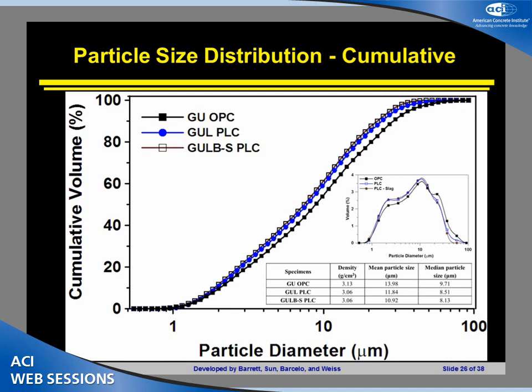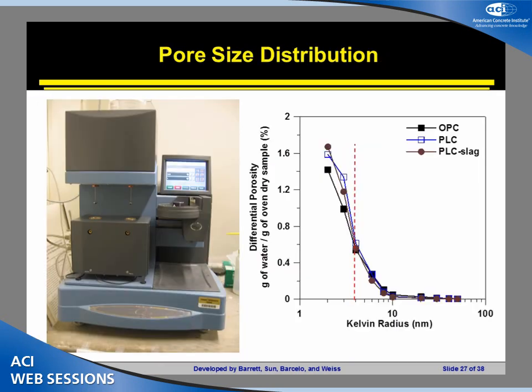Here you can see that there's a slight shift to the left, but we don't see that sort of parallel shift. And what you notice if you look at the frequency distribution or the derivative of this curve, you see essentially what we're doing is we're losing a lot of these big particles, these 30 micron, 40 micron, 50 micron size particles, and we're replacing them with some of these smaller particles in the 2, 3, 4 micron range, and those are really that ground limestone. So what we're doing is we're getting rid of, on a microstructural level, the basketball size particles. We're getting a lot of softball size particles, and we're ending up with a few ping pong ball size limestone particles in the system.